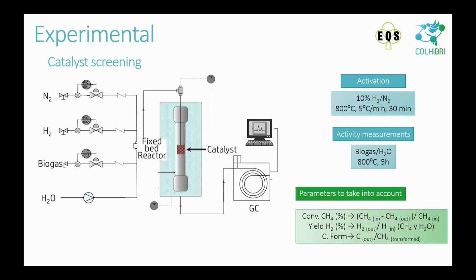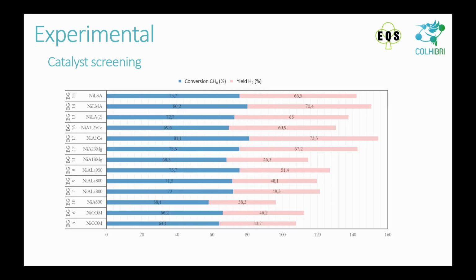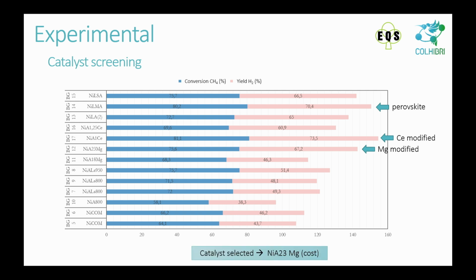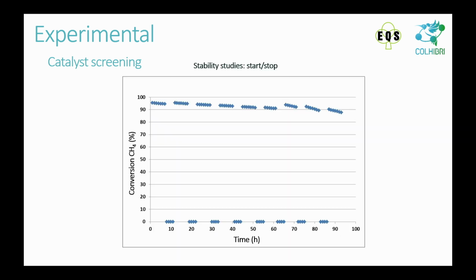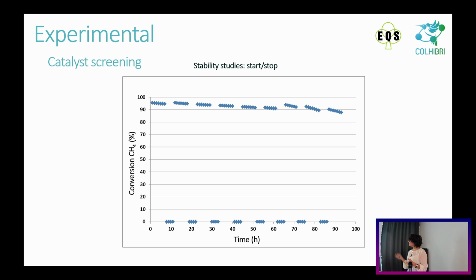The parameters that we need to take into account to choose the best catalyst are the conversion of methane, the yield of hydrogen, and also the formation of carbon. So here we show the conversion and the yields of the different catalysts that were synthesized, and you can see that the ones that show the best activity are the perovskite, one of the catalysts with cerium modified support, and the other with magnesium modified support. And even though this magnesium modified catalyst doesn't have the highest activity, it is the one chosen because it has the lower cost. So the next step is to study the stability of this catalyst, and we've done it in that same fixed bed reactor for several cycles.